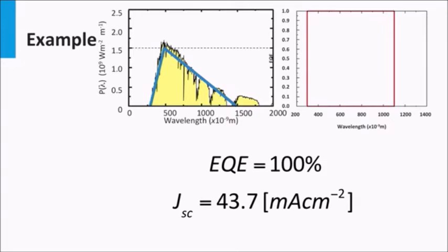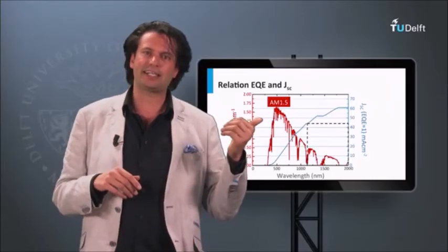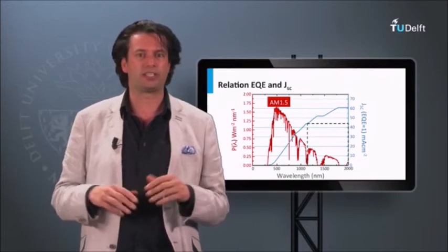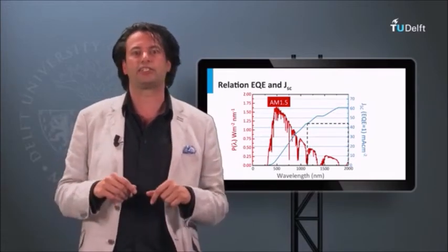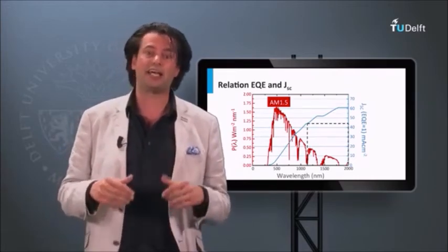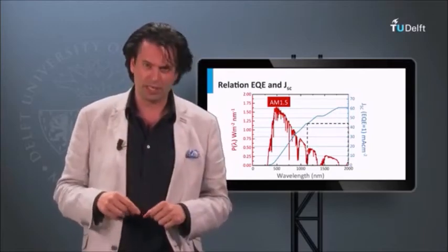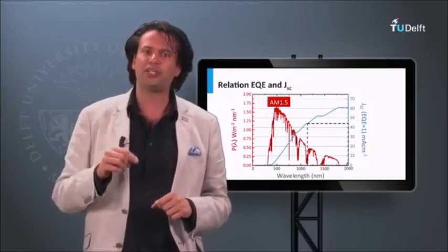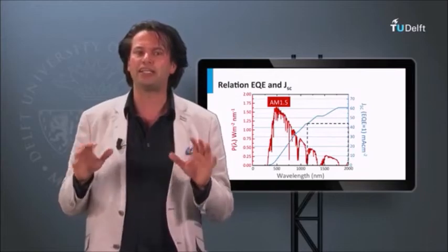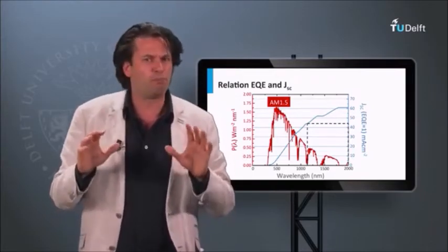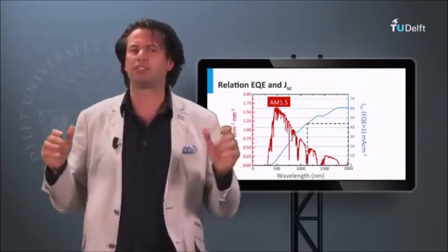If we would have an EQE of 100%, we estimate a current density of 43.7 milliamps per square centimeter. This is again in excellent accordance with the theoretical current that crystalline silicon can generate, as we have seen earlier. This provides you an easy tool to make realistic estimations on the possible photocurrents that various materials can generate.